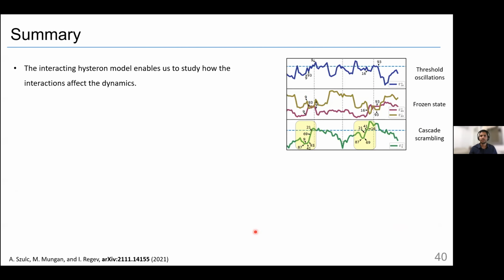So to summarize real quick, we saw that the biggest benefit of our model is that we can track the changes of gamma plus and gamma minus all the time and after every switching. And we saw interesting things. The threshold oscillations, by the way, we can also see in molecular dynamic simulations. The frozen state and cascade scrambling are effects that are, at least now, harder to observe in molecular dynamics, and we are working on it to try to confirm that.